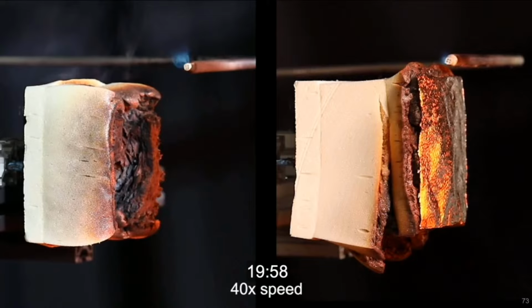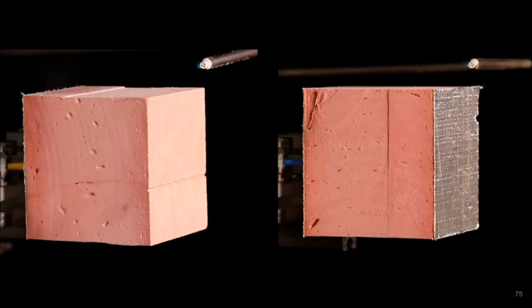So now I'll show you the same comparison for Kingspan Cooltherm K15 insulation, and you'll notice some differences in behavior. Again, a trigger warning. I'll show two videos of experiments on Kingspan Cooltherm K15 insulation at the same heat flux, 50 kilowatts per square meter, both with and without the foil facer in place. In this case, on the left, we will see that ignition doesn't occur as rapidly as was the case for the Celotex RS5000, taking about 16 seconds for the sample without a foil facer.